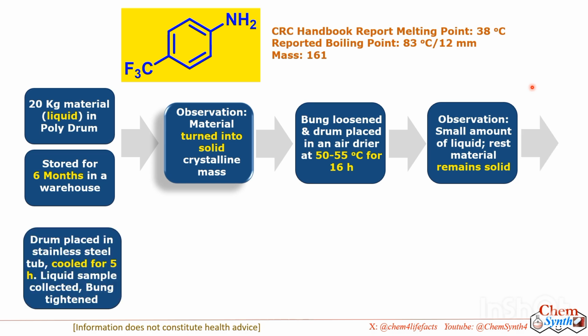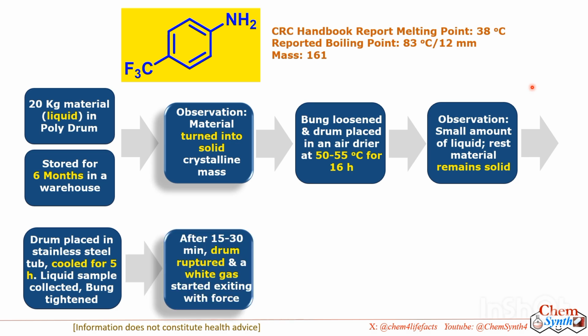Now they brought that material back to room temperature. At that time they collected that small quantity of liquid and kept the drum closed with the cap. But after 15 to 30 minutes, they saw that the drum ruptured completely and a white gas started exiting with force.